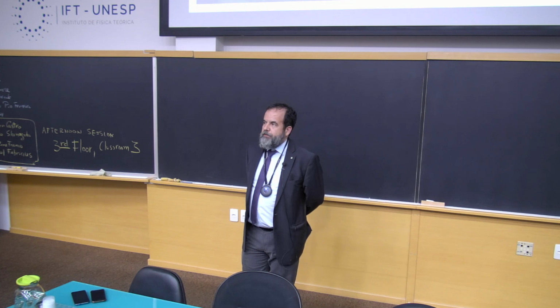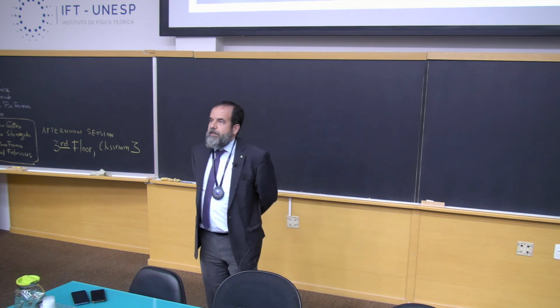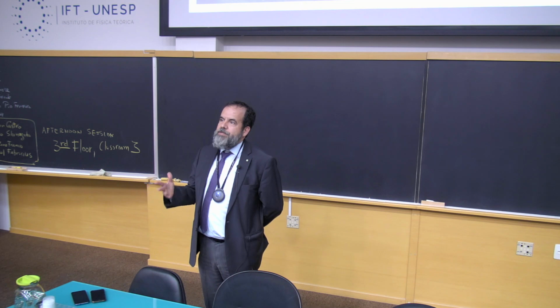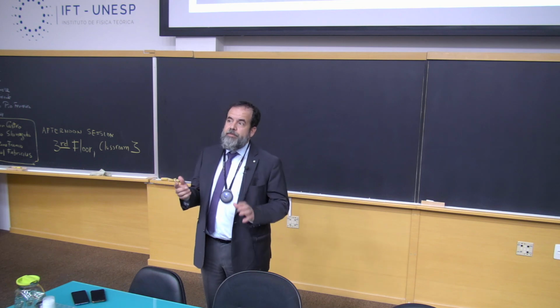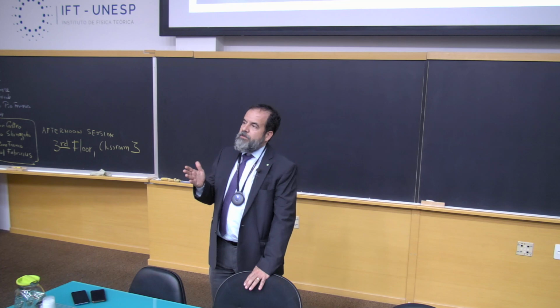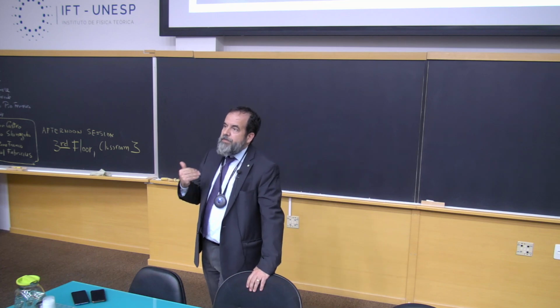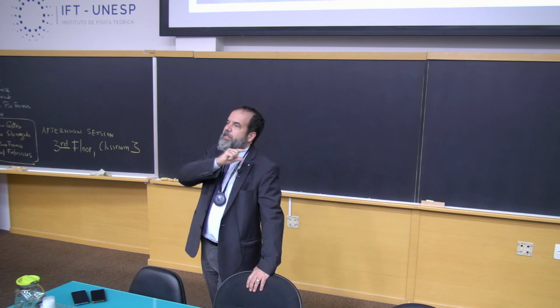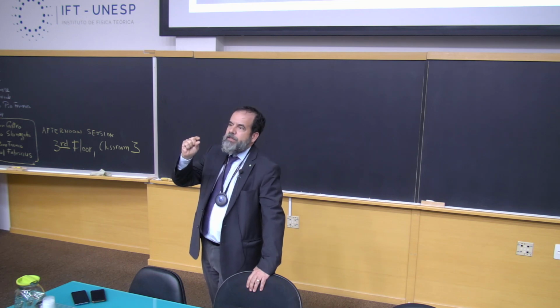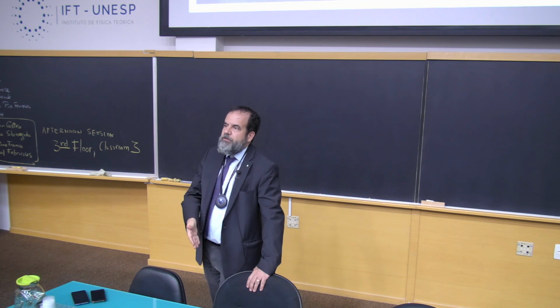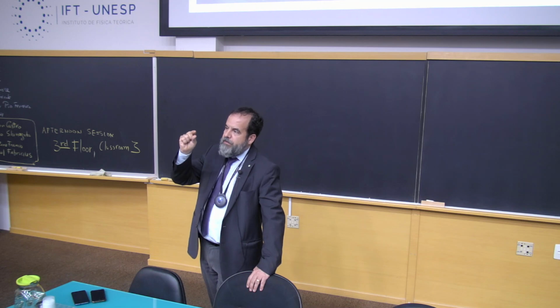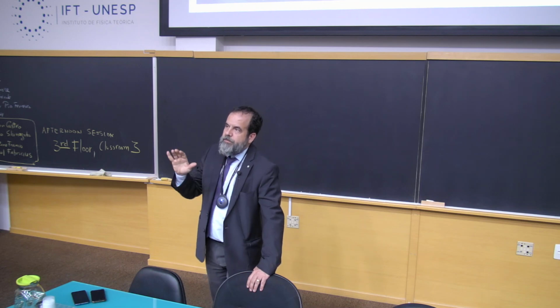Well, that's a very nice question. The problem with silicon, let's start with silicon, is that it's fundamentally not so nice for this kind of application in principle because of the indirect gap. So you already have some problems that you lose a lot of light coming. So you cannot do as thin as we are working with. You can't do 200 nanometers because it will basically become transparent or semi-transparent, and you lose a lot of light. So you have to have it thicker. So you need thicker materials for silicon to start.